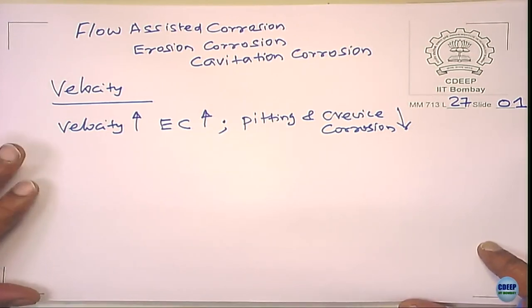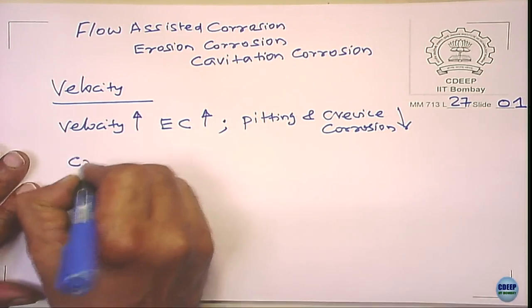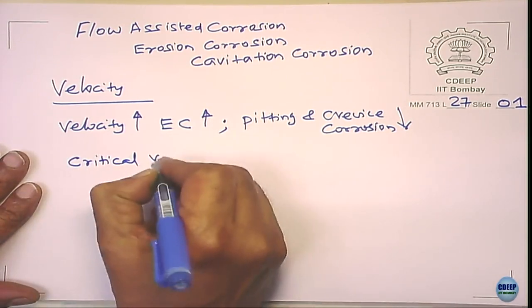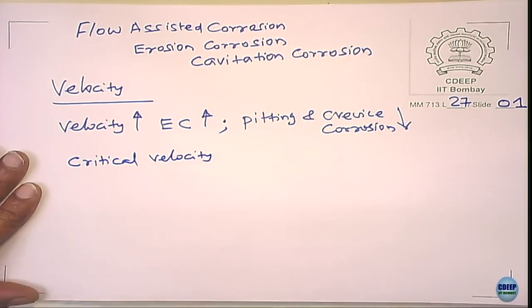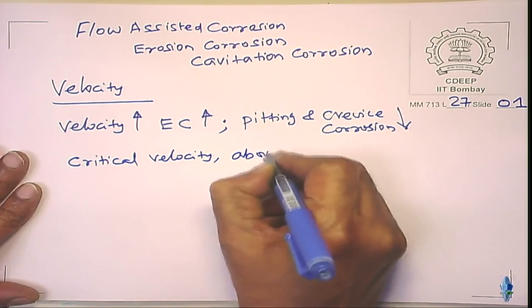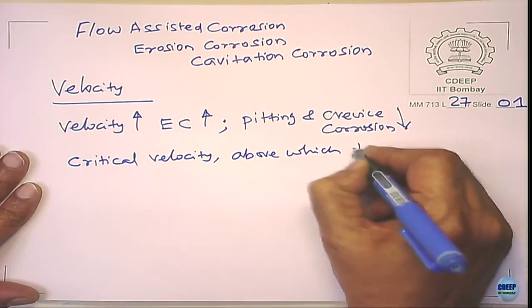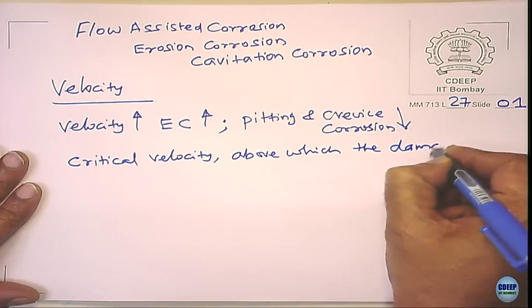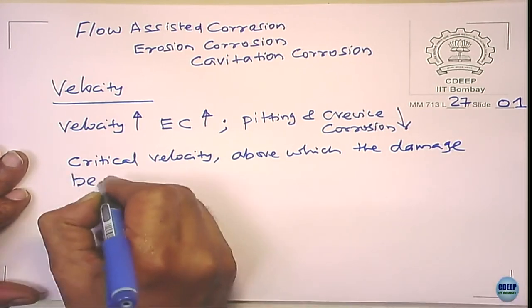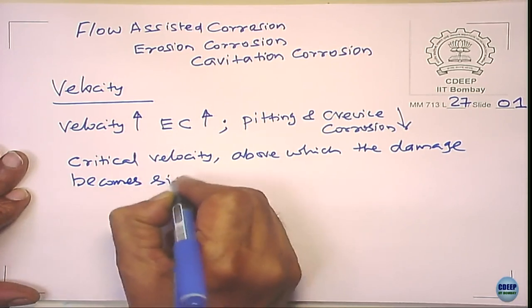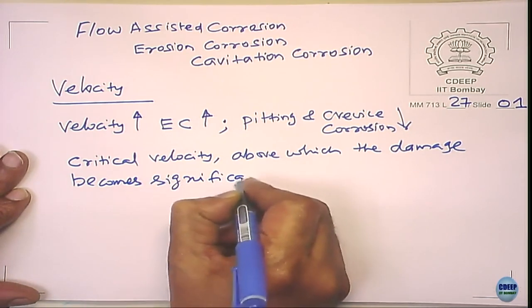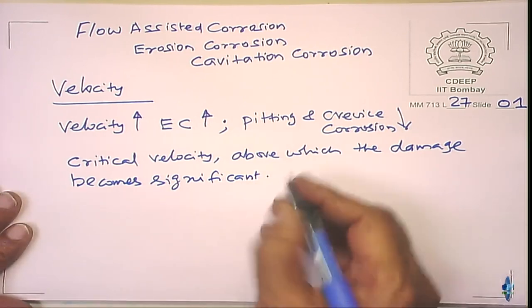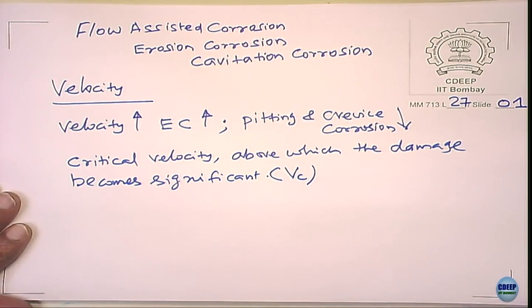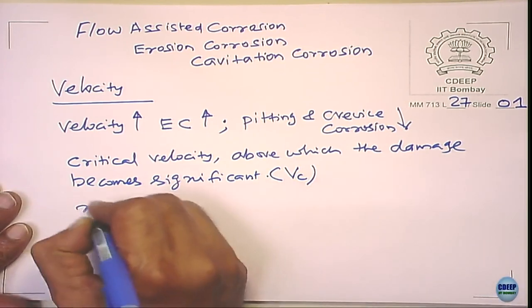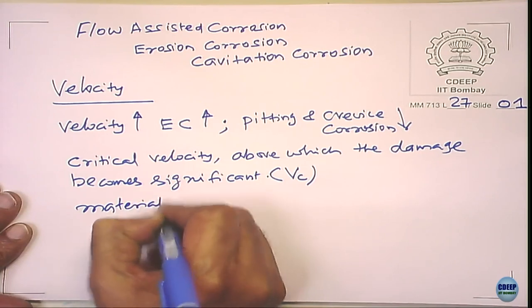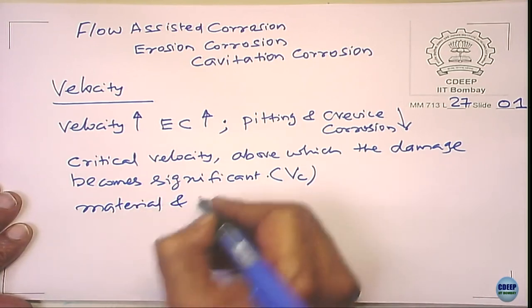It is also necessary to understand that there is a critical velocity above which the damage becomes significant. And this critical velocity that we talk about is material dependent, and of course environment dependent.